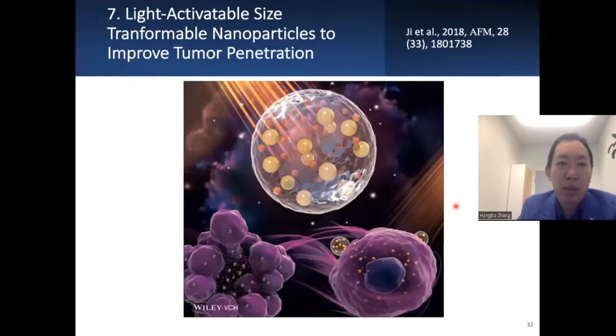And we can also use some other way to regulate and improve this tumor penetration, because, as I mentioned, to penetrate deep inside the tumor is very important for effective tumor inhibition. So as I mentioned, to accumulate the nanoparticle in the tumor, you would need a nanoparticle which is 100 nanometer size. But if the nanoparticle is very small, for example, less than 10 nanometer, then they are too small and can be easily eliminated by the kidney from the body. So in that case, it's also not good.